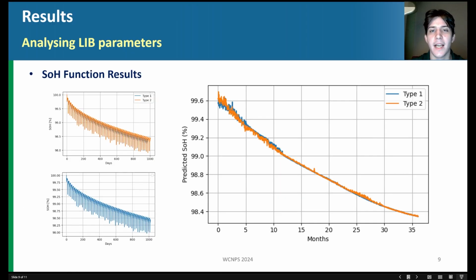Finally, to present the hybrid approach case, here is a comparison of PyBaMM and the LSTM hybrid model. From the graphs, the results proved there is similarity, consistent with PyBaMM SOH forecasts from the same projected scenarios dataset. While not exactly accompanying the same cyclical behavior, the hybrid approach had a much lower computational cost of about 30 minutes compared to PyBaMM's 3-day processing time. With this side-by-side analysis, the hybrid approach showed that machine learning models trained on physics-based data can be a powerful tool for long-term battery degradation prediction.